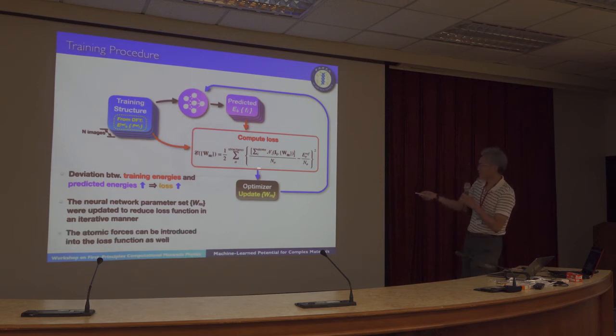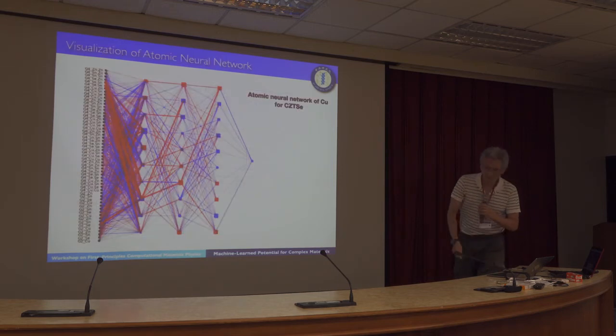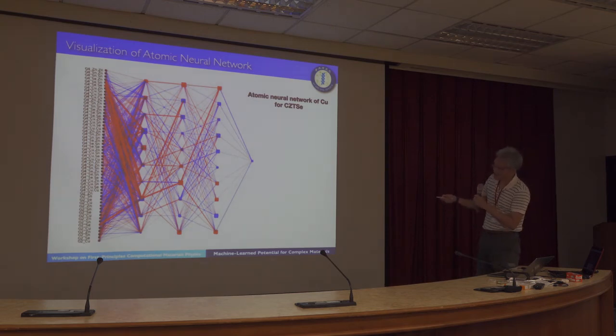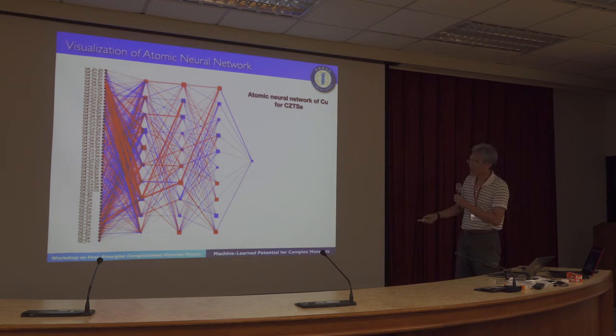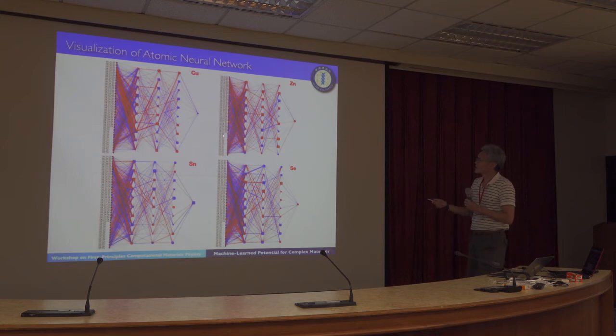Because I have limited space on this slide, I only put energy as the target, but actually we can also include atomic force in this loss function. And this is how the atomic neural network looks. This is the input feature vector, and this is one example for copper in CZTSe material. Red means a positive weighting number, blue means a negative one, and the thickness of the line corresponds to the absolute value of each weighting parameter. For CZTSe, you need to prepare 4 different atomic neural networks, one for each element.